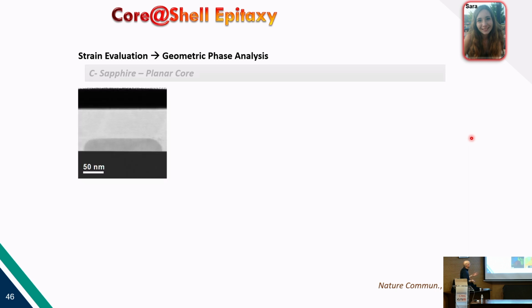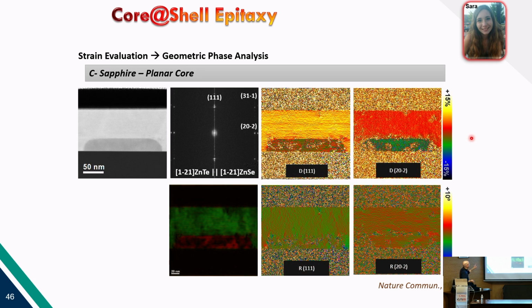But what happens here? When you are using a flat surface instead of circular, what you have is that there's no rotation, so it's perfectly flat. This is another way to relax your material. It's just flat, and it can be grown like this.